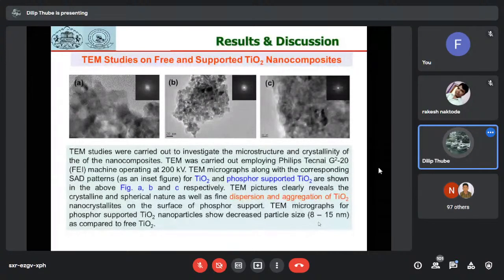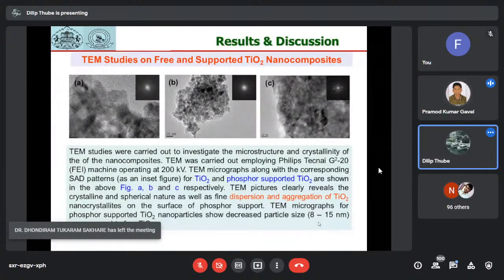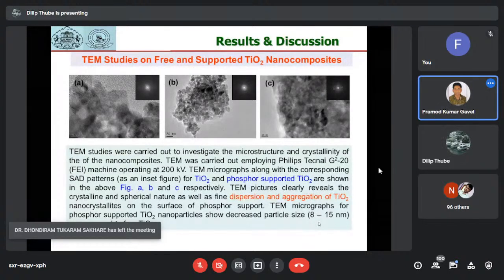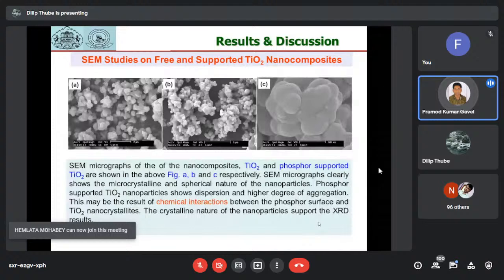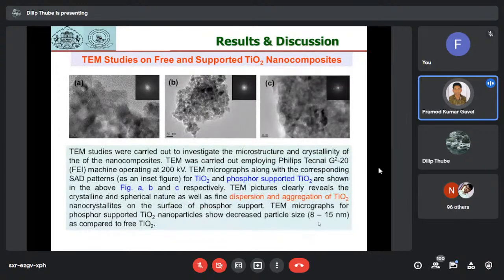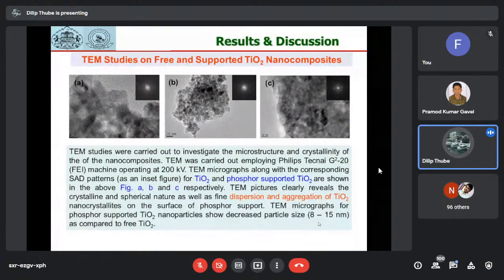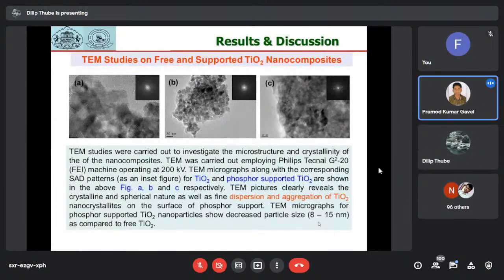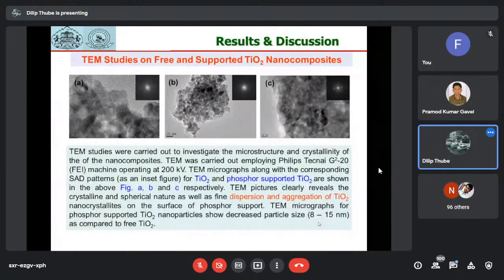This slide shows the TEM images. Sorry for disturbing you. What is the size of the TiO2 supported on the phosphor material? Can you tell the size of that material? The nanoparticles on the surface of phosphor material, it is aggregated. It is about 8 to 15 nanometer. We can find out by using TEM images, right? Yeah, so it is mentioned over here.